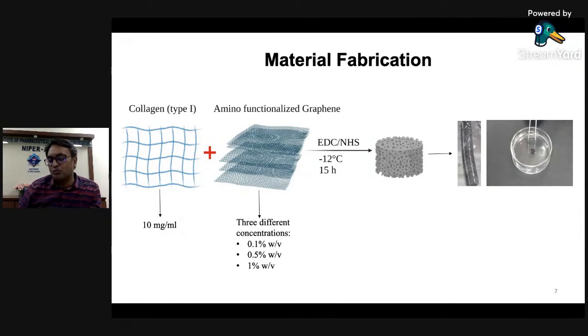And it has certain stimuli, both mechanical as well as electrical. However, the electrical and mechanical properties are not exactly matching up to the mark of the spinal cord. Thus, we have added graphene material in the starting. And we thought that by adding graphene, it will be able to make a robust material which will have excellent electric conductive properties, because graphene is known for electric conductivity, which will be imparted in the scaffold. It also modulates the mechanical properties of the material.